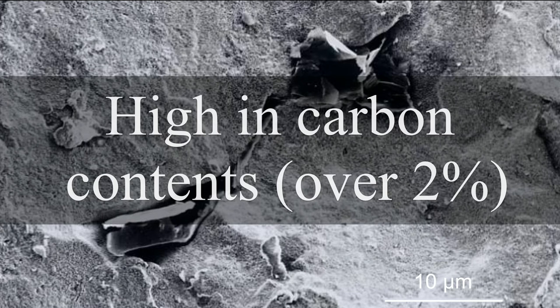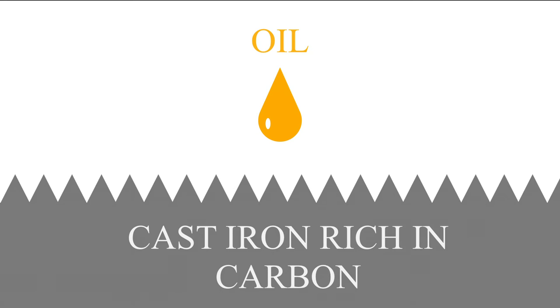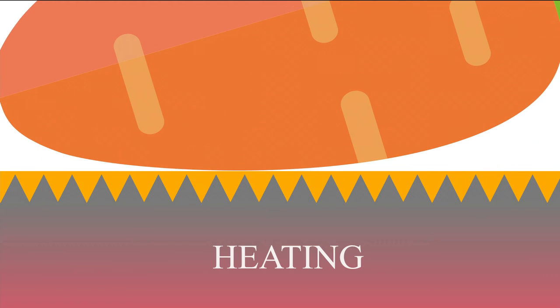This is really different in the case of the traditional iron pan, because the traditional iron surface contains a lot of carbon — a material that bonds very well with oil — and it has a microstructure. Those aspects of the cast iron, rich in carbon, help contain the oil on the surface even when water comes out of the food. And eventually: no sticking.